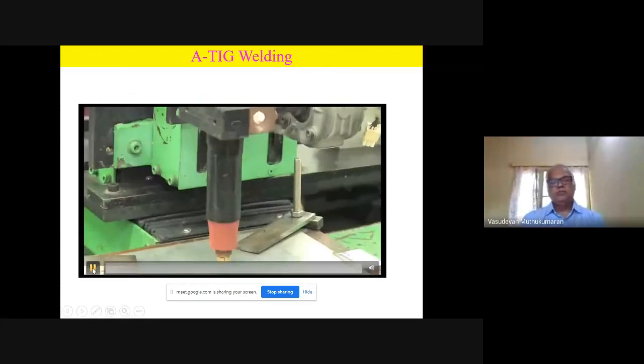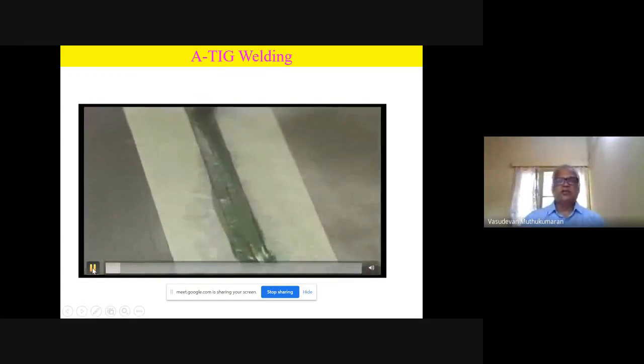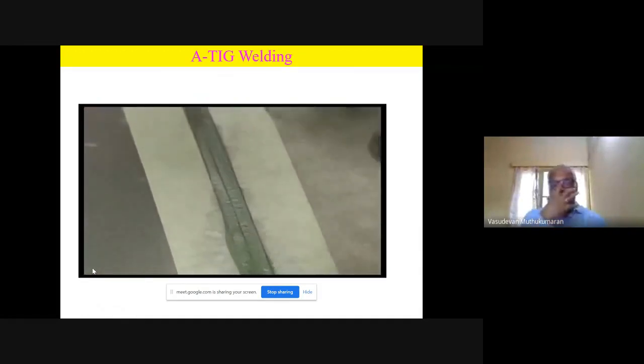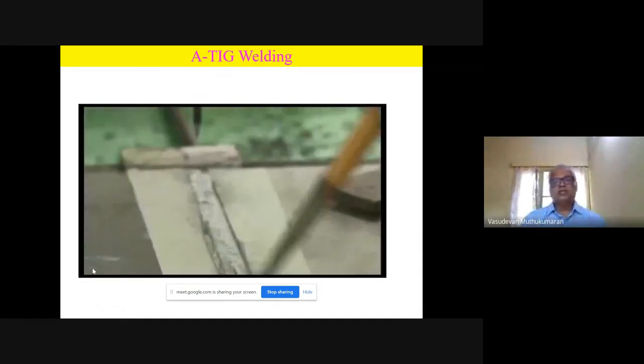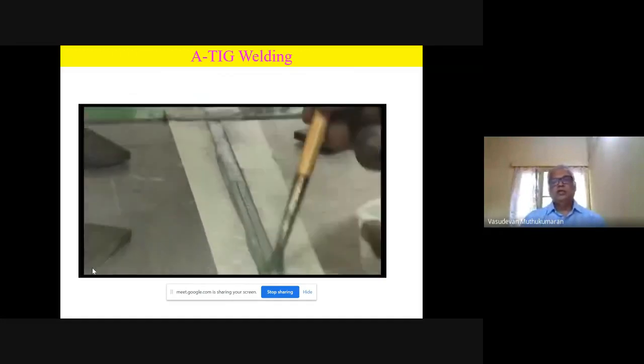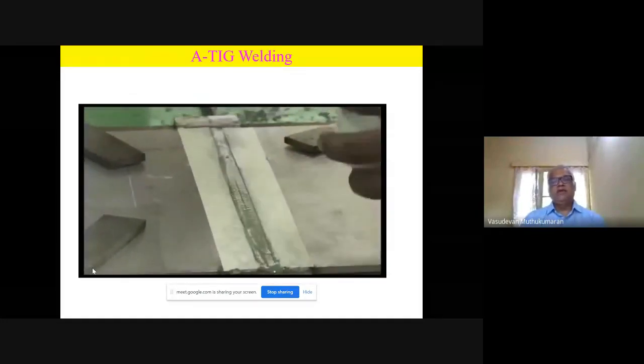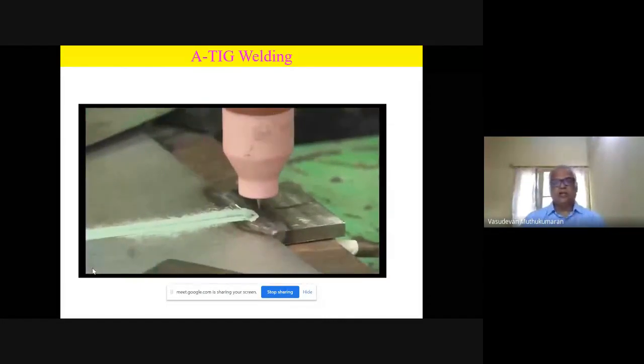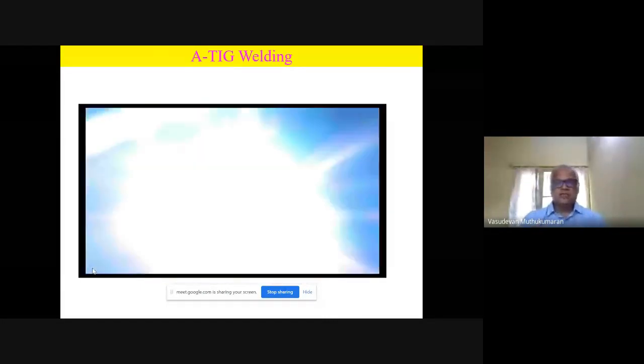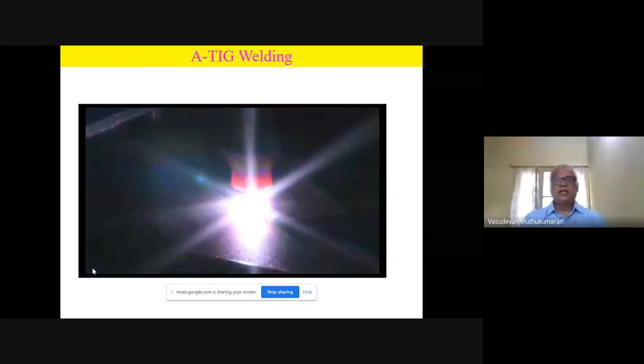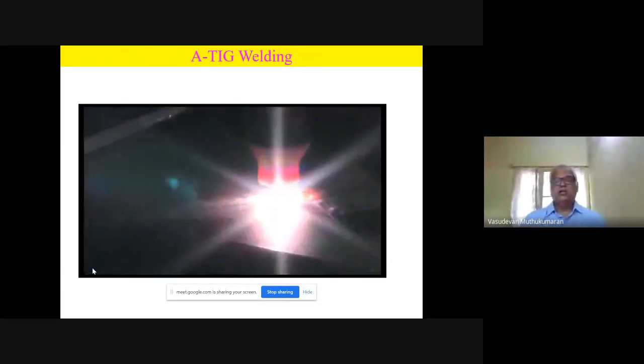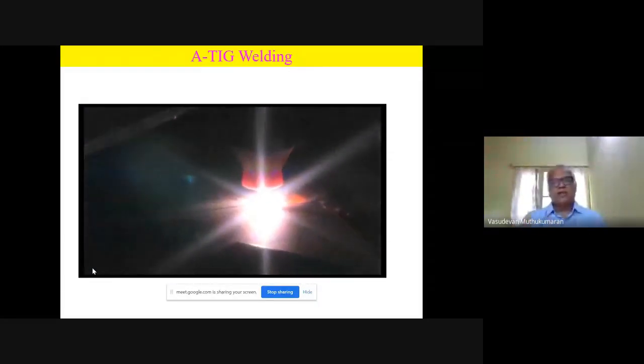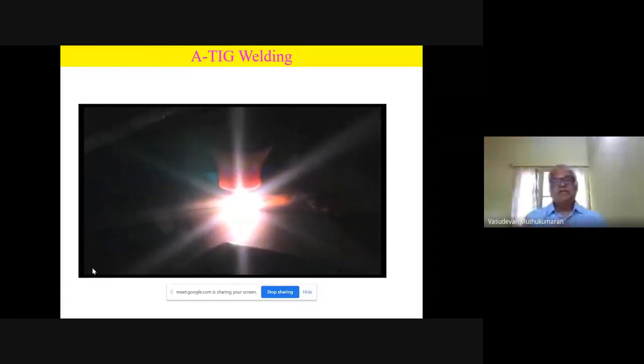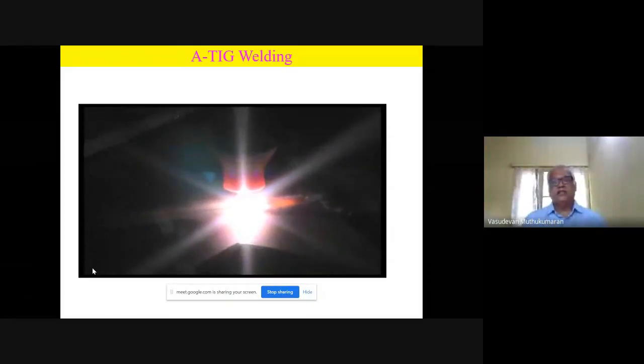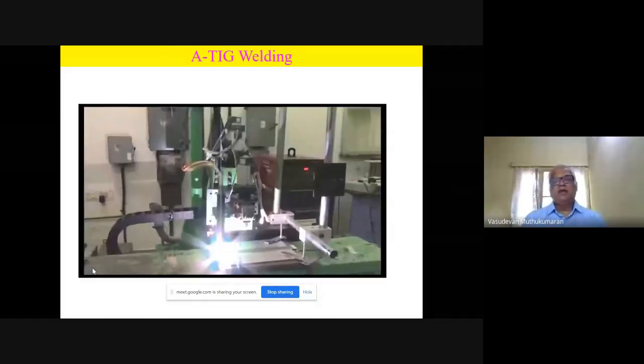Please see the video. Here we apply a thick coating of flux on the joint area. It enhances the process performance manifold. See, in automatic TIG welding, we cannot get more than 3 mm penetration, but by applying a coating of flux to enhance the penetration, in a single pass we could get 12 mm of penetration in stainless steels. So we can apply a single pass and clean. Since then we have been using this process for welding various thickness components, even plates and